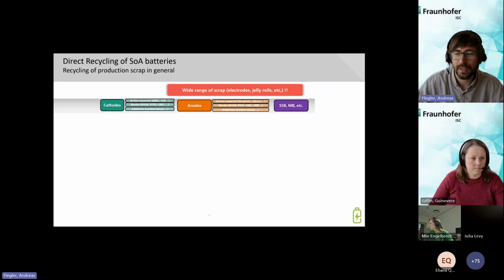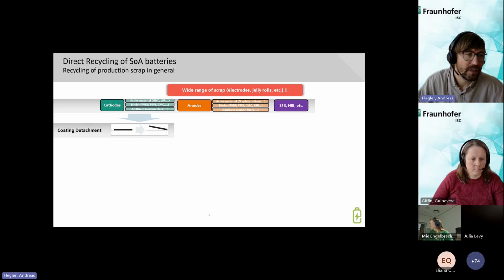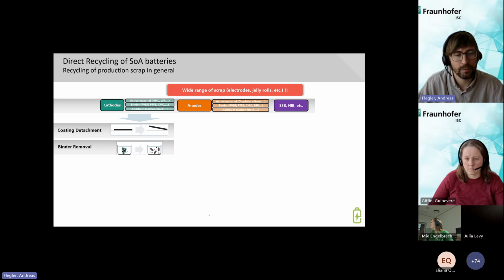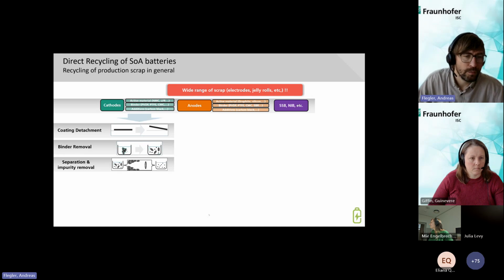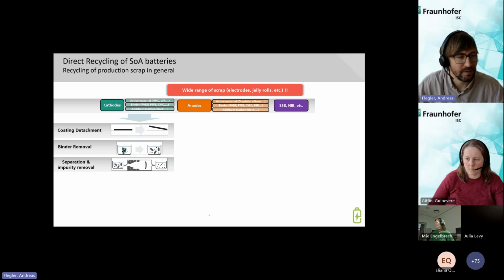And for REUSE, we want to build up one specific path for the direct recycling of LFP. We divide it into 4 main processes. The first step, when we use electrodes, is the coating detachment. The second part is the removal of the binder, so that we can separate the active materials from carbon black and also remove the binder. And then we go further to classify the materials and also to remove some impurities when we have something in the black mass, so that we have the active materials and the carbon black and the binder separated and can bring them into a second use.